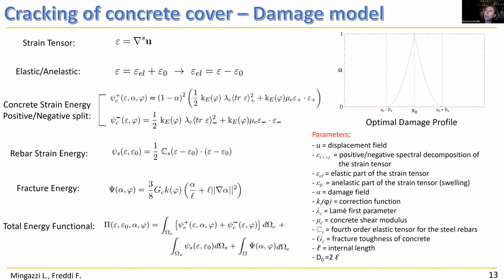So I'm just considering asymmetric behavior of the concrete because it's much weaker in traction rather than in compression. And I'm considering a decoupling behavior of the deformation, elastic and inelastic deformation, in order to keep into account the swelling of the bar. So this is the expression of the strain energy of the bar, and this is the expression of the fracture energy of the cracks. And this is the complete expression of the functional.